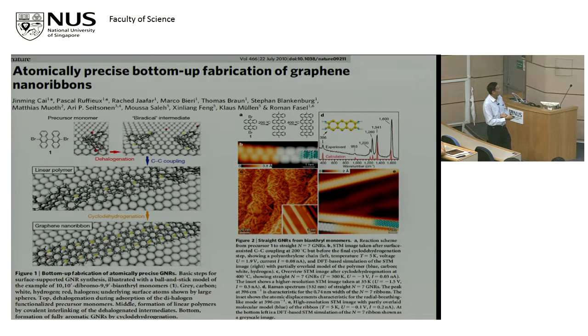So we decided to try this, inspired by the work. So we didn't do it first. Klaus Müllen's group and Fasel in Germany, Switzerland, they did the bottom-up approach, put this molecule, DBBA, polymerized it, dehydrogenated it, so it became a nanoribbon on the surface, on a catalytic surface. And then it made all these nanoribbons bottom-up by assembling molecules, the chemistry way, which is a good way of doing it perfectly. No lithography needed. Of course, the challenge then is how to transfer all this out. But nevertheless, it was, in principle, a demonstration of how you can make very thin nanoribbons, because it has to be very thin before you get a measurable band gap.